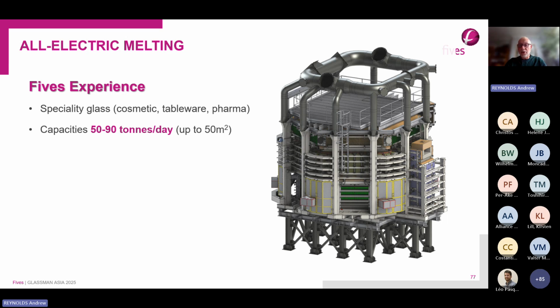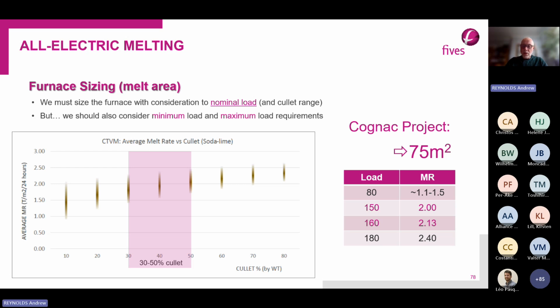Electric melting, as I said, is not new. It's already quite widely applied in cosmetic, tableware, and the pharmaceutical industry in furnaces ranging up to about 50 square meters, 50 to 90 tons per day. When I say 50 square meters, I'm talking about the melt surface, which is the primary way of sizing furnaces. For the Cognac project, we were working at similar melt rates to cosmetic glass because the quality levels were quite high, and those melt rates are something like just over 2 tons per square meter, 2 tons of glass produced per day per square meter of surface.